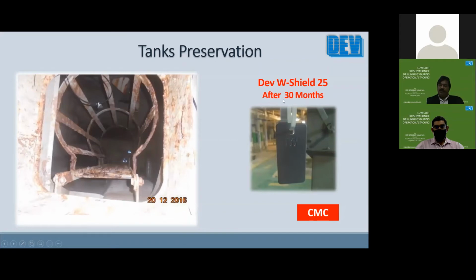And you can see, even after 30 months of preservation, we are installing a corrosion monitoring coupon like this to enable ongoing monitoring and assurance, which I said was not available in the traditional technologies. With this, you can see even after 30 months of the one-time preservation, the corrosion monitoring coupon remains in the same condition, showing that all the tank internals remain in the same condition without any further deterioration.